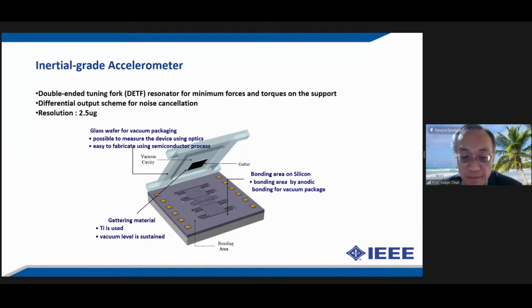And if you make a little bit of modification on that one, then you can make an inertial grade accelerometer. So my team worked on this one, for the missile application. And as in the bottom of this figure, it has two identical proof masses, and then the comb drives, again. And it's called the double-ended tuning fork type, and it's using a resonator, for the minimum forces and torques. And then a differential output scheme is used for noise cancellation. And then the resolution was up to 2.5 micro-G for an inertial grade accelerometer.